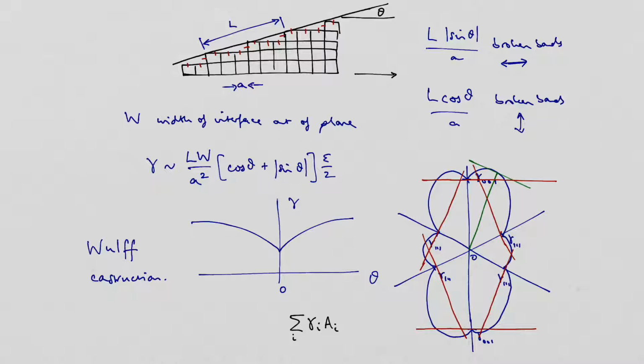If you imagine I took theta down even more, I would just get these steps, and I get broad plateaus of essentially 001 with line defects, these steps in between them, because that's actually the lowest way to organise that surface. So that's typically what a vicinal surface will be characterised by: these plateaus of singular surfaces and then line defects along them. And then general is anything else.